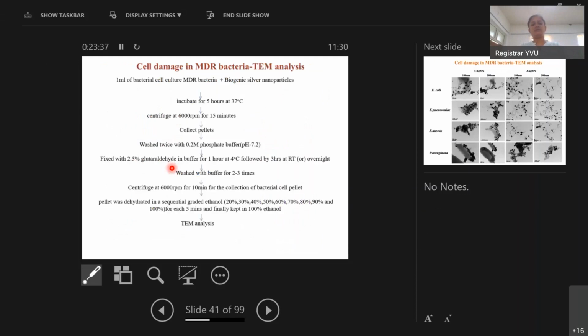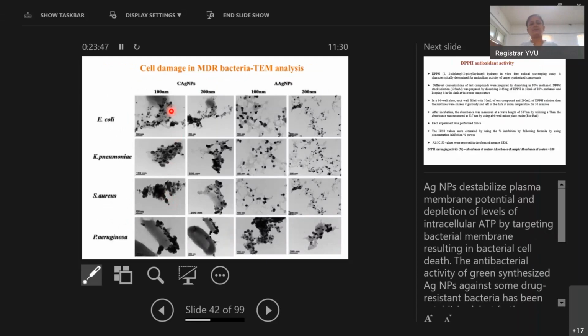After that, I investigated the cellular damage of multi-drug resistant bacteria through transmission electron microscopic analysis. This is the protocol I have used, and these images I got at 100 nanometers and 200 nanometers using lower and higher concentrations of green synthesized silver nanoparticles treated with 4 multi-drug resistant microorganisms. This E. coli at 100 and 200 nanometers shows the cellular damage clearly. Azadirachata indica silver nanoparticles also show bacterial cellular damage. Both Catharanthus roseus and Azadirachata indica nanoparticles show effective cellular damage in the 4 multi-drug resistant microorganisms.